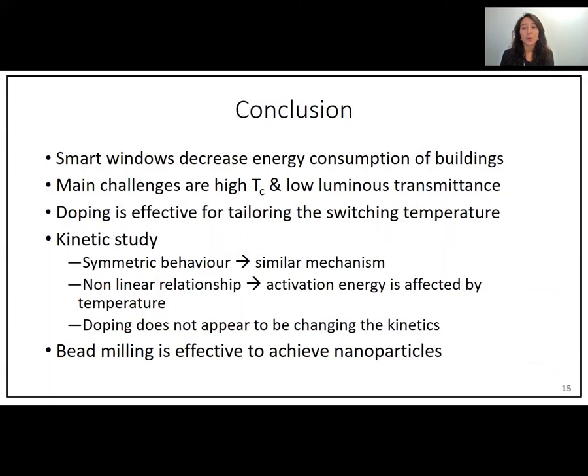To conclude, smart windows have a great potential in decreasing the energy consumption of buildings. The main challenges are the high transition temperature and the low luminous transmittance. These are both addressed. The first one is addressed through tungsten doping, and then a kinetic study was also carried out. From this study, we found that the symmetric behavior suggests that the mechanism of the structural phase transition is similar in both directions. The nonlinear relationship is because of the activation energy being temperature dependent. And lastly, doping does not seem to change the kinetics. Additionally, the bead milling was effective to decrease the particle size from the micron size to nanoparticles.